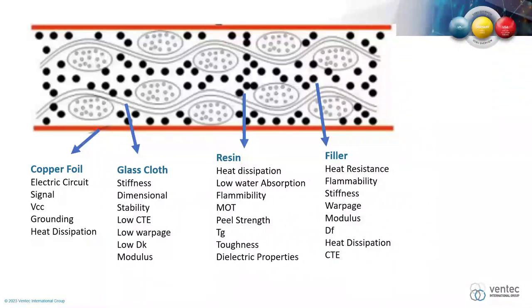The different types of glass cloth will have different stiffness. They'll have different levels of dimensional stability. Some are low CTE. It could help with low warpage, low DK, and obviously the modulus, the resin itself. So we modify the resins or put fillers into the resins to basically modify them to perform better electrically or to perform better thermally, or to reduce the CTE. So it's also used for heat dissipation. There are resin systems out there that are purely designed to dissipate heat.